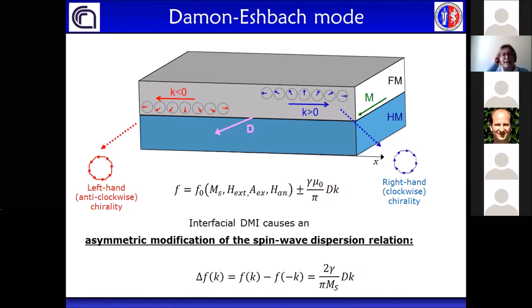In particular, it has been found that when DMI is present in the spin wave dispersion, there is an additional term which linearly increases with the spin wave vector with an opposite sign depending on the spin wave polarity. So the interfacial DMI causes a frequency difference between spin waves propagating in opposite directions, which linearly increases with the spin wave vector, where D is the effective DMI constant proportional to the DMI strength. Using Brillouin scattering, it's possible to measure this frequency difference and obtain a quantitative evaluation of the effective DMI constant.